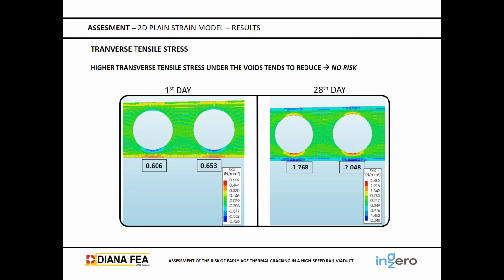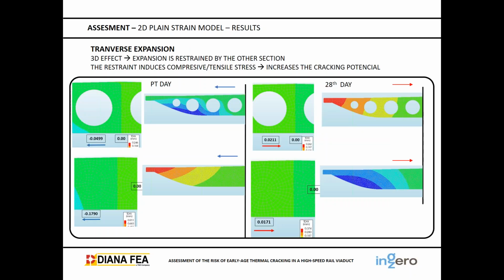Regarding the transverse tensile stress, we see that even on the first day it was higher under the voids. And if we look at the transverse expansion and compare the two sections, the void section and the gross section, we see that even though they have the same behavior with expansion or compression, they have different values. So it has to be a 3D effect in which expansion is restrained from one section to the other. This restraint induces compressive or tensile stress, which increases the cracking potential.